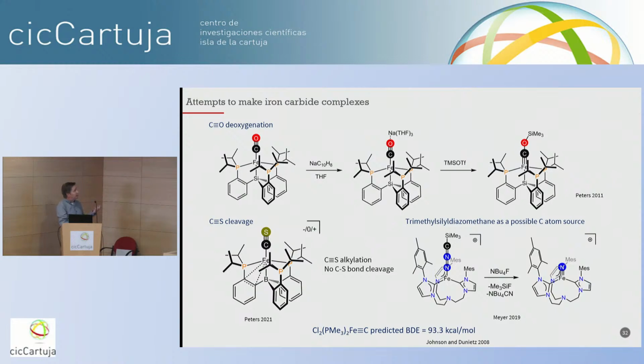One way you can make carbides, and this is how the first example was made, is by deoxygenation of CO ligands. This has been attempted with iron, and Jonas Peters' group has become the closest. They can reduce CO with reductants, they can functionalize it, but then that's where they get stuck.